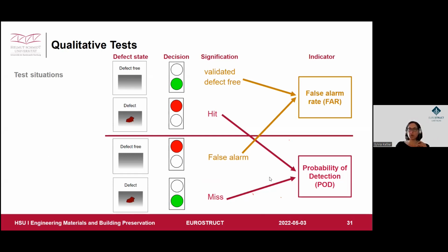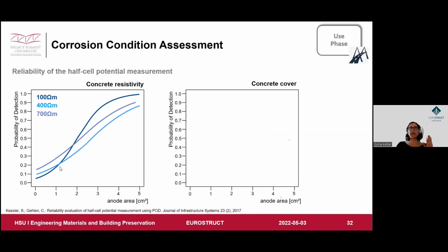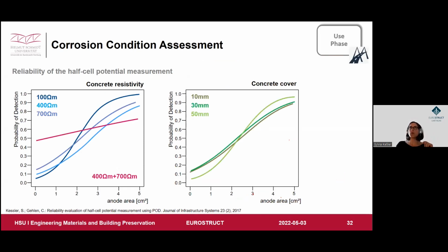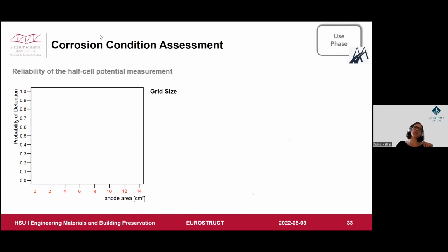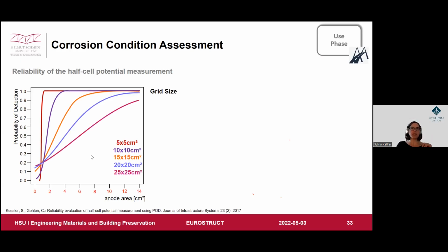Here I want to focus much more on the probability of detection, especially for corrosion detection. We did a very comprehensive evaluation of that, but I would skip a little bit of the slides, having in mind the time. I think the most important slide is probably this one. We have the probability of detection in dependence of the defect size, which in case of corrosion is the anodic area, just the area on the reinforcement surface where the anodic partial reaction takes place. And we have different grid sizes, so the scan size of your electrode, and you see that the probability of detection decreases with increasing grid size. This is typical. This is something you would probably expect.